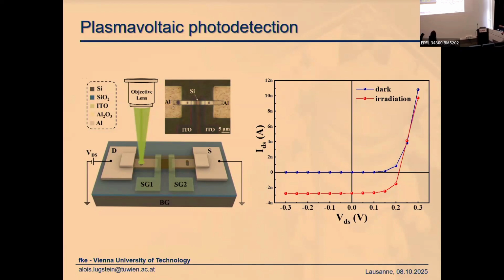If the laser is polarized in this direction, we get almost no signal. If it's polarized in this direction, where you can effectively launch plasmons, you get a really nice signal. And we have the same laser power in both experiments, so we can exclude the heating, and with that, I think it's convincing.